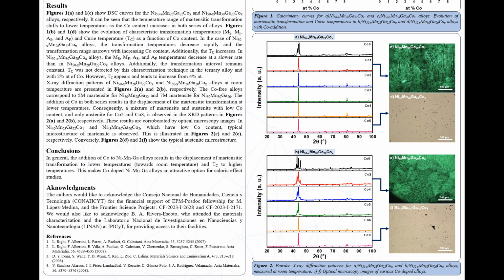In conclusion, the addition of cobalt to nickel-manganese-gallium alloys results in the displacement of the martensitic transformation to lower temperatures, towards room temperature, and of Tc to higher temperatures. This makes cobalt-doped nickel-manganese-gallium alloys an attractive option for caloric effect studies.